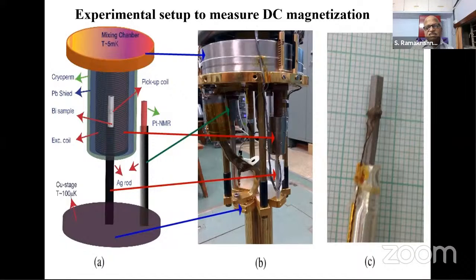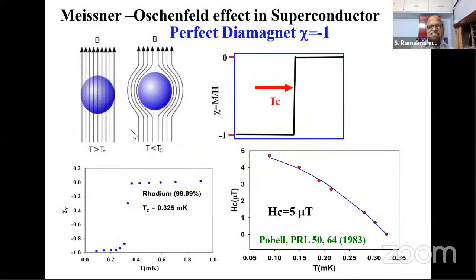Not only that, then we need to measure the magnetization. So we have to again employ a SQUID magnetometer, where we build the basic magnetometer and assemble all the magnetometer part. Only the sensor we buy from outside. The rest is all built by us. So what we see here is the bismuth with a pickup coil, which goes into a SQUID. Then you can measure its magnetization.